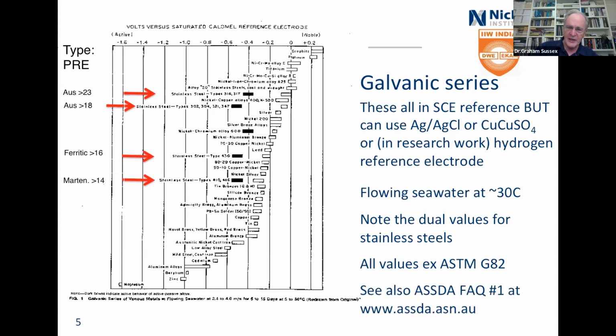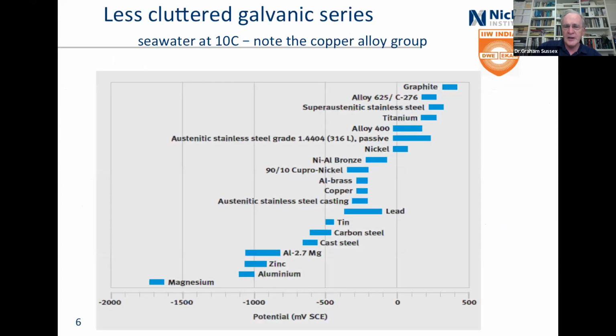There's an FAQ on the ASSDA website, which has got much the same sort of thing. This is a similar thing, but rather less cluttered, just to show you a little more clearly. And it's for seawater at 10 degrees C. What I'd like to point out to you, though, is this group of alloys: nickel-aluminium bronze, 90/10 copper-nickel, aluminium brass, copper, even austenitic castings, are all at about the same potential. So if you connect them together, then it's really not going to be a defect in terms of dissimilar metals.